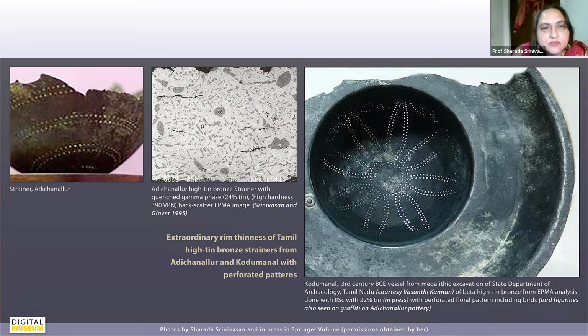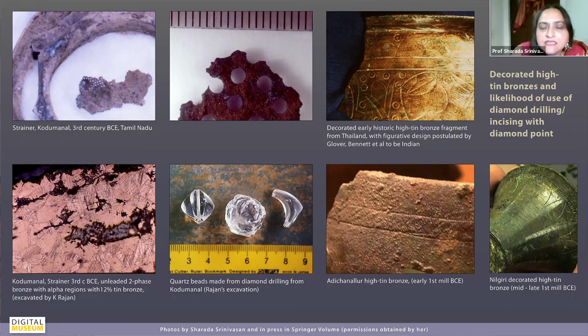You have the strainer from Kodumanal, and you can see these very, very tiny holes, in this case about 1 to 2 millimeters, and how they actually went about making such tiny perforations. Now in Kodumanal, they were also using the technique of diamond drilling, which of course goes back to the Indus and Harappan tradition. And you can see these quartz beads, which seem to have also been cut with a diamond wheel, because quartz, again, is a very hard material. And in fact, Rajan, who excavated Kodumanal, had many years back even recorded the use of diamond bore drilling in around the region of Kodumanal, which has now completely died out.